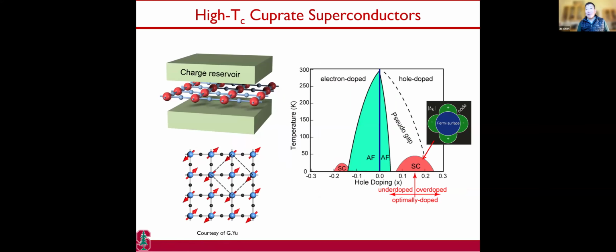So this is the old subject of the Cuprates, and much of the effort has been on the hole-doped side, where Tc is higher. But generally, this is a single-layer system, and you have the copper oxygen plane as shown in this case, and also the charge reservoir holding charges in the system.